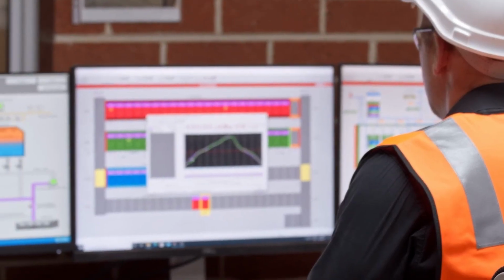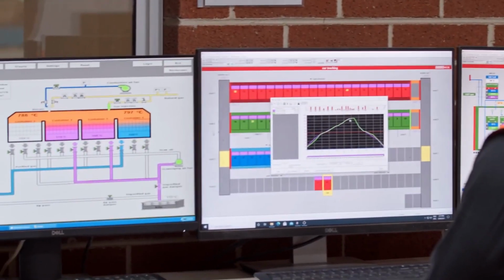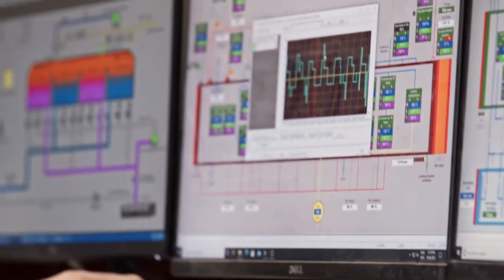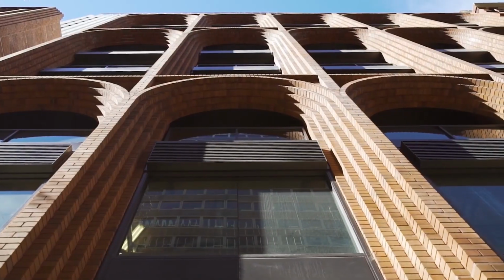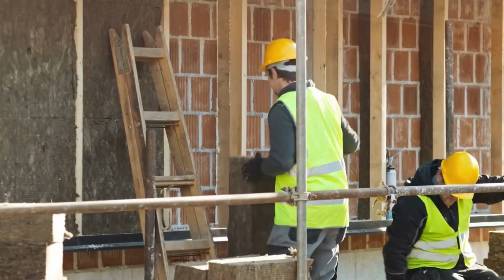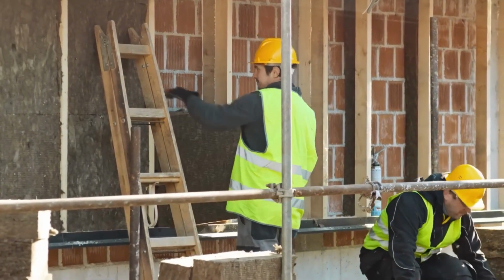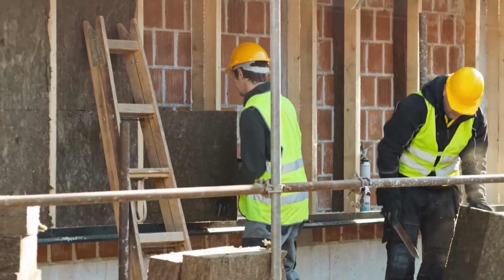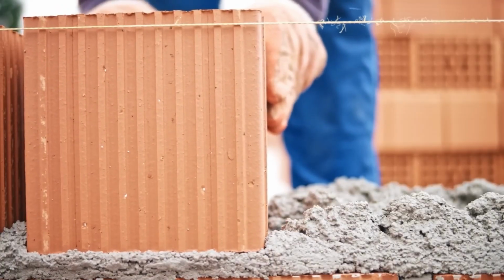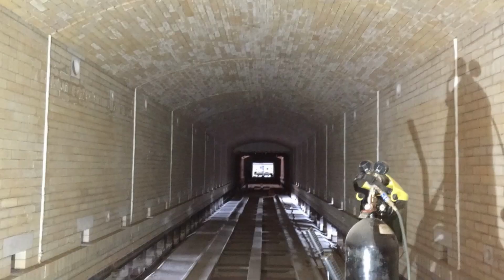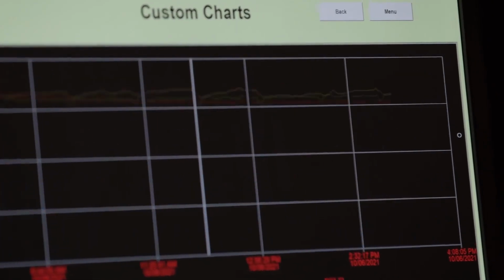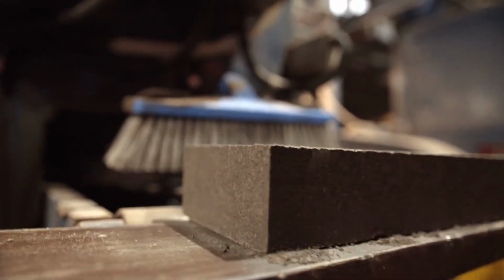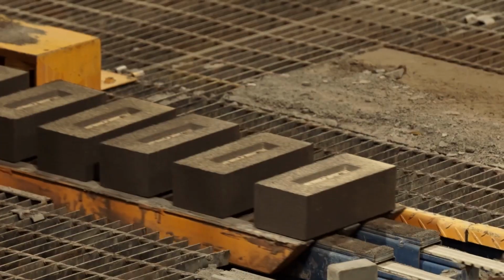The minimum acceptable result for a standard building brick is 10 megapascals of compressive force, sufficient to support the loads imposed by a multi-story structure. Engineering bricks used in more demanding applications such as foundations or retaining walls must meet significantly higher thresholds. Water absorption measures how readily a brick takes on moisture. A brick with excessive absorption is vulnerable to frost damage. Water that penetrates the material and then freezes will expand, causing the brick face to spall and crumble.